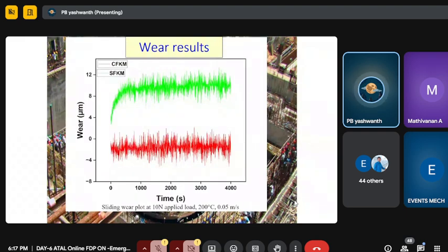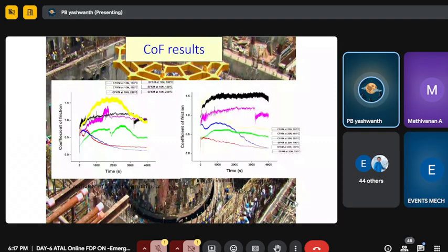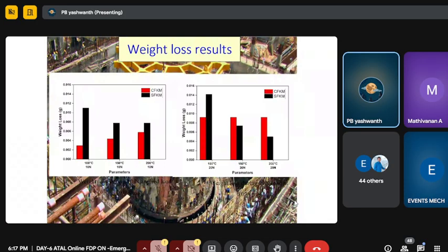All the results were in the same kind of representation, where carbon had lesser wear. This gives you the consolidated coefficient of friction results. In that also, a better coefficient of friction is shown by carbon. You can see the weight loss comparisons, in which all the experiments show carbon reinforced fluoroelastomers have very little wear compared to the silicon based.